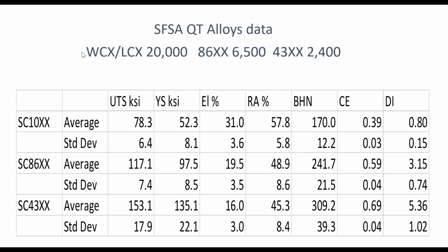We have over 20,000 points for the carbon steel, 6,500 data points for the 86, and for the 43, we have about 2,400. So one of the main reasons I wanted to talk about this is to try and encourage other people to participate in giving us data and to show that we're getting real value out of this data. So we need to extend this to the 4100, to the CA6NM, to LC2-1, so that we can get all of this data. Now I'm using it at the moment. This is the WCB stuff.